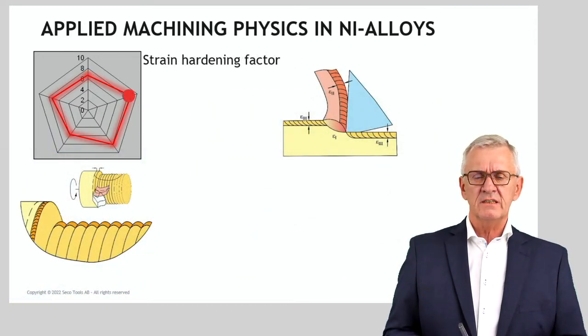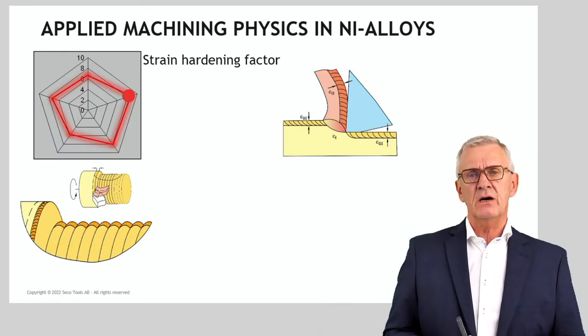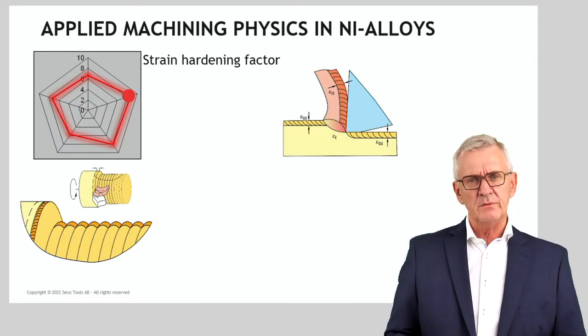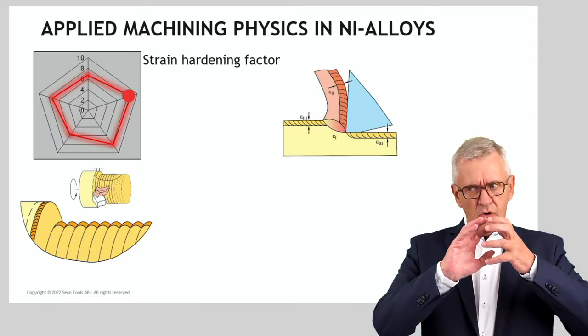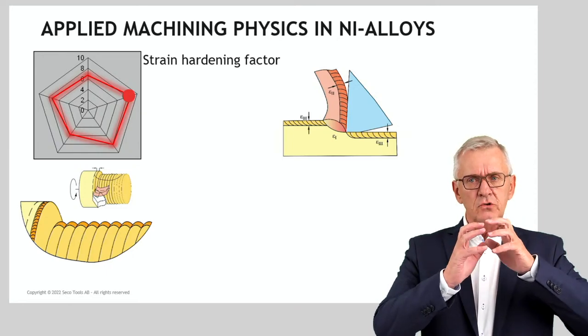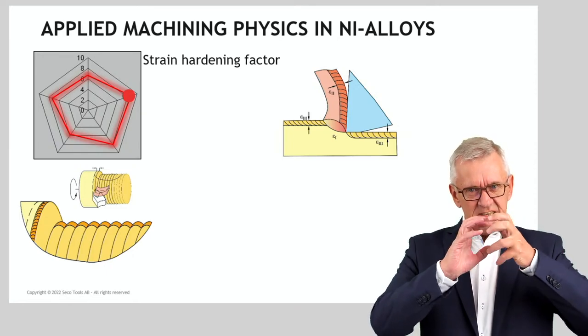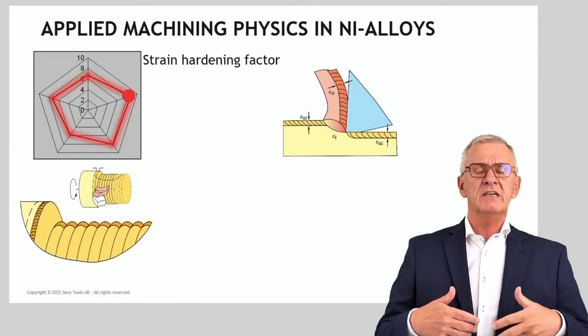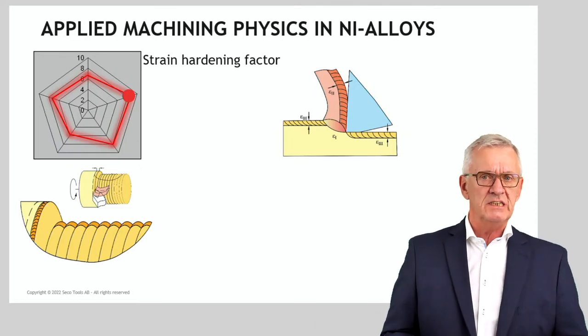More problematic, really problematic, could be potentially in nickel-based alloys, is strain hardening factors. Now, what is strain hardening as a physical thing? It means that if you have a material and if you deform the material due to strain, to stress that appears in the structure, the material shows a tendency to harden.